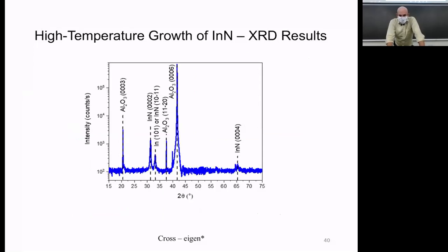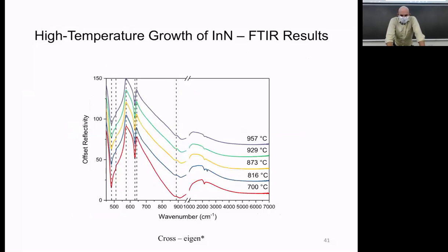When we look at XRD, we see something similar. They all look very much the same. We get a high, sharp peak. We can model it with a little broad peak as well. Nothing interesting there. When we start to look at FTIR, again, you see we have the main peaks that are related to sapphire. So all the dashed lines are related to sapphire, and the features in between are related to indium nitride. And then we have these things over here, and according to literature, there's nothing in indium nitride at that energy level. So that's a problem that we need to understand.